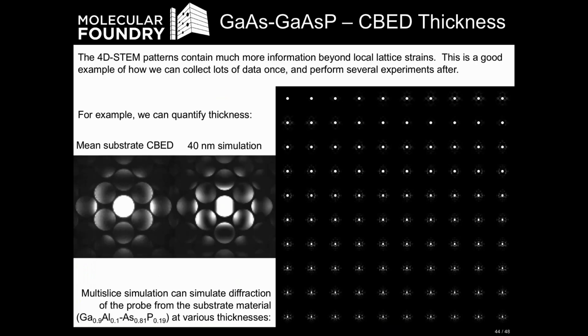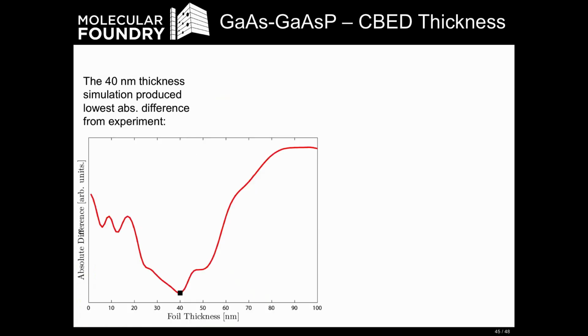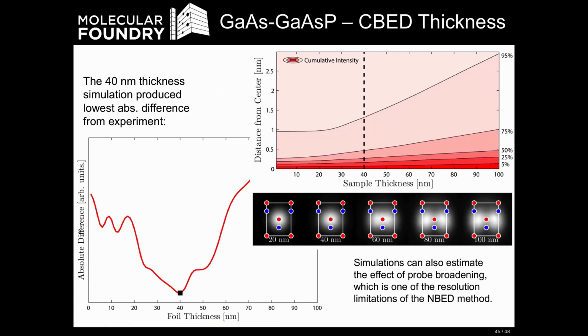So we can be pretty sure our sample is 40 nanometers. And I could have gone through this same exercise with sample tilt, for example, and I could have resolved exactly how close the orientation is between the substrate and the film, let's say, just by measuring the asymmetry in the diffracted disks, as long as I can do a multi-slice simulation here. Okay, and so this is just one last plot.